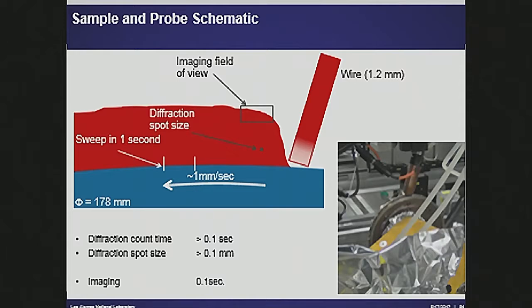The measurements that we made, and sorry, the resolution is a bit poor here, a last minute problem. There were two sets of measurements that we made, right? And actually there's a couple of things to think about. We made the weld with the wheel rotating, right? And the reason that we did that was that we wanted a fixed geometry, whereby we could actually move both an imaging viewer and a diffraction spot relative to the weld pool, right?